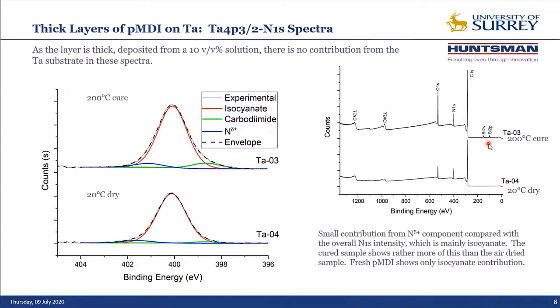We go to a lab where there's an oven for curing composites, and what do we see? Polydimethylsiloxane, PDMS is ubiquitous amongst the compositors, so that's where we think that came from. If we look at the cured film first, we've got our isocyanate peak here. Now this is the peak that we saw on the PMDI that was immediately introduced into the spectrometer, only there was no broadening to either side. Now we've got some broadening, which is a carbodiimide material. This is a result of an interaction between 2 diisocyanate groups. It's well documented, we often see it, so that's no surprise. But we've also got this nitrogen with a slight positive charge on it over there.